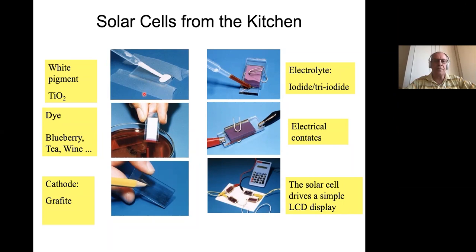You heat it up to 400 degrees for about half an hour. You bake it in a way, and then you have formed this TiO2 layer, which is then a sponge in nanoscale, let's say. It's a porous electrode. So when we dip it into the dye solution, the dye goes in and sticks to the surface. And here is the fun part of the lab, really.